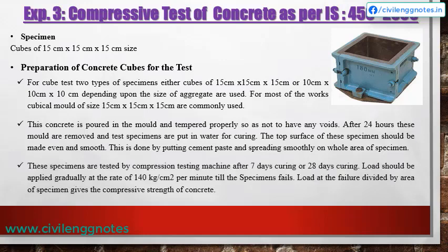Specimens are tested by compression testing machine after 7 days or 28 days of curing. Load should be applied gradually at the rate of 140 kg/cm² per minute until the specimen fails. Load at failure divided by the area of the specimen gives the compressive strength of concrete.